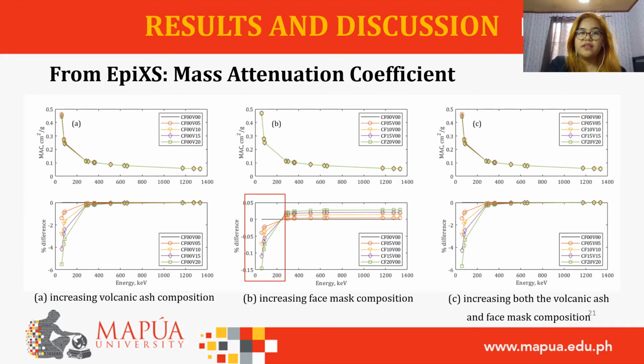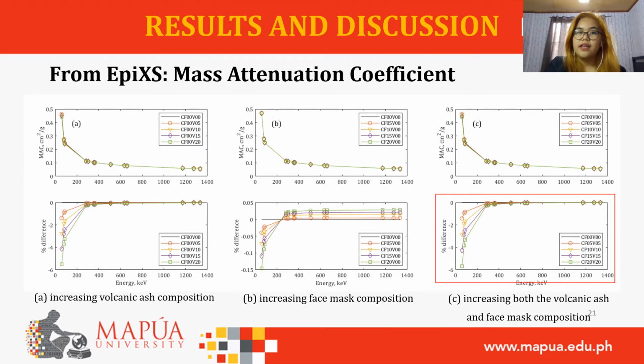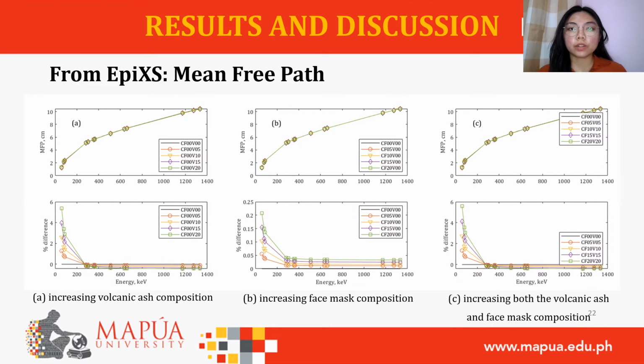For case 2, there is an inverse trend between low and high energies. Therefore, increasing the face mask composition will be favorable for high energy applications. Lastly, for the third case, a similar trend to case 1 can be observed because the sample's volume contains up to 20% of volcanic ash, whereas the face mask is only up to 0.20% of the total volume. The trend and scale of the MAC values are found to be consistent with previous studies of normal weight concrete by Un and others, composite concretes with metal oxides by Tekin and others, and composite concrete with perlite materials by Agar and others.